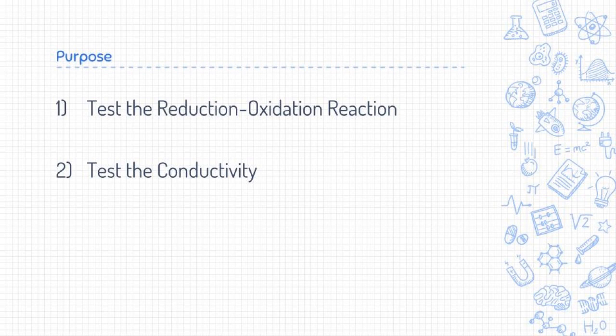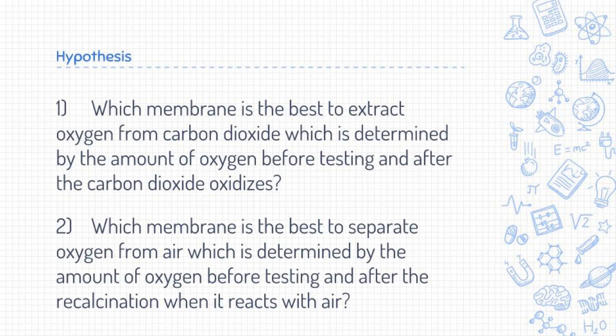The control sample has Ceria doped with zirconium in 4 trials with one of the following second dopants: iron, copper, yttrium, manganese. The 2 main questions we are trying to answer examine which membrane is the best to extract oxygen from carbon dioxide, which is determined by the amount of oxygen before testing and after the carbon dioxide oxidizes. The second examines which membrane is the best to separate oxygen from air, which is determined by the amount of oxygen before testing and after the recalcination when it reacts with air.